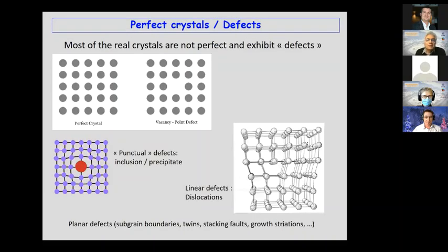Most real crystals are not perfect and exhibit defects. We sketched here a perfect crystal where all the atoms are well arranged, and one very common defect is a vacancy. All crystals have vacancies because this is thermodynamically stable. But you have a lot of other defects which are not stable but exist, like precipitates, which distort the lattice all around, or like dislocations, which are linear defects which correspond to glides in the crystal. In addition, you have planar defects, subgrain boundaries, twins, stacking faults, growth striations, and so on.